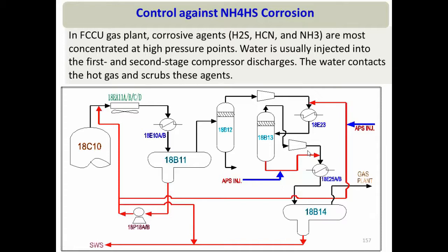So what we understand based on this discussion is that water washing is a solution not only for desalting, but also for fouling problems and corrosion problems; water washing serves many purposes. One, it avoids salting and under-deposit corrosion. Also it avoids ammonium bisulfide corrosion because of high concentration. Also it is used as a slip stream. By using it as a slip stream, they are just throwing out the cyanide ions and all those things. So that is very important in nature. And even in an amine unit, water washing may throw out the heat stable salts. So there are many important purposes of water washing in this system.